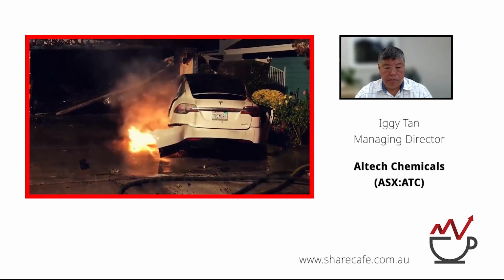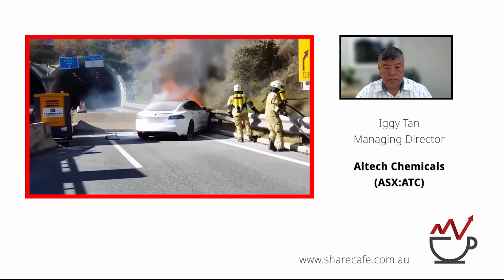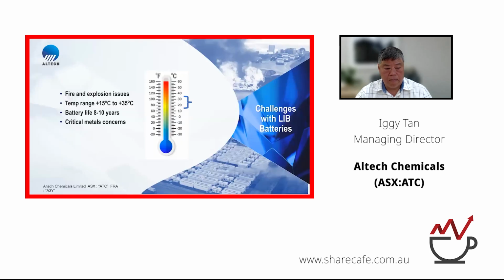As you know, one of the challenges of lithium-ion batteries is devastating fires and explosions. The other main issue is that the lithium battery only operates in a very limited temperature range, between 15 degrees and 35 degrees. When you get down to 0 degrees, the lithium battery capacity drops to about 70%. So it slows down, and the reason for that is the liquid electrolyte in the battery becomes more viscous.